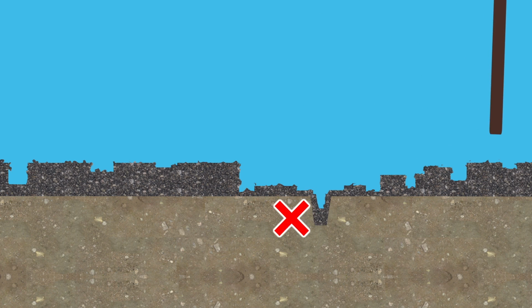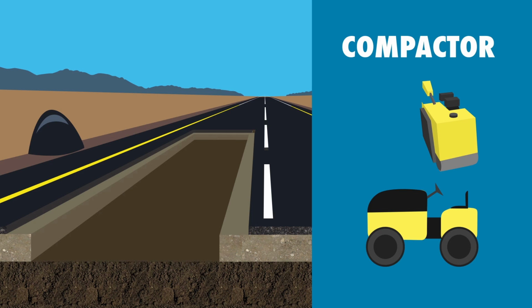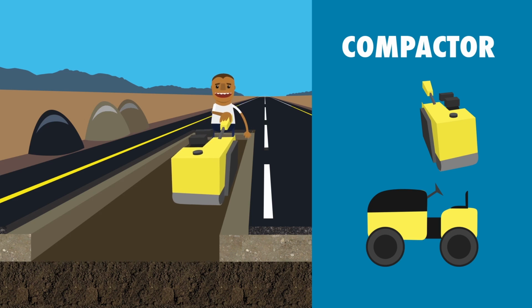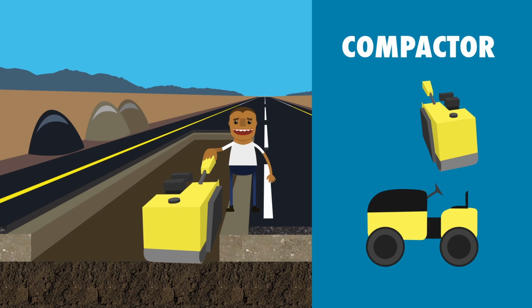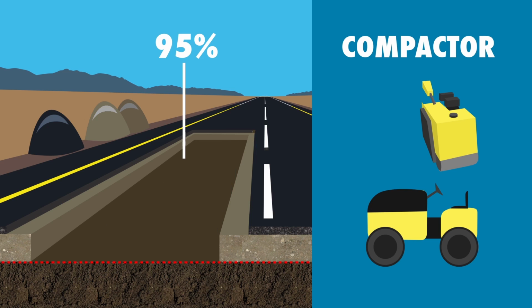Material from one layer may not be mixed with that of another layer. If any mixing is caused by the contractor, the contaminated layer should be removed by the contractor and replaced with other approved material at the contractor's own cost. Once the base has been excavated, using a compactor, walk behind or side on, compact the floor of the patch to 95% compaction. If the floor material is dry, wet slightly. Once compacted, the subbase should be 150 mm to 300 mm below the final base level.